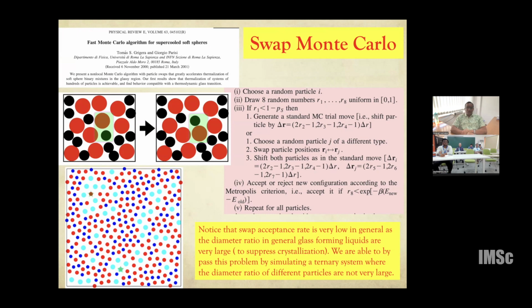This may sound like a very trivial change in the Monte Carlo method, but it turns out this is one of the best ways to speed up the relaxation process. And I will show some results soon that just by swapping two particles of different types, the relaxation can be sped up. This will be useful only if you are dealing with systems which are binary or polydisperse. For example, in a binary liquid, you can take a big and a small particle and swap their positions.